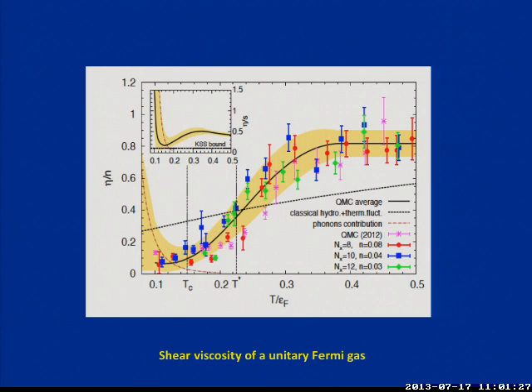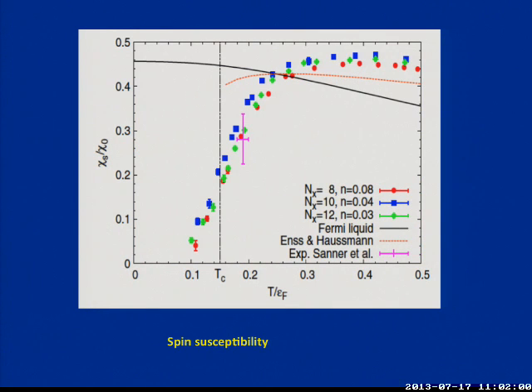Basically, the contribution comes at very, very low temperatures only. Even with that contribution, above this temperature the phonons essentially don't contribute. So the limit is not quite obtained, because that limit is 1/4 pi, which will be something like 0.08. It will be here. This is about 0.12, 0.15, something like that. Piotr, what's the exact number? Yeah, you remember? But no, that number is actually not for this. This is entropy over entropy density. So it's not the thing.